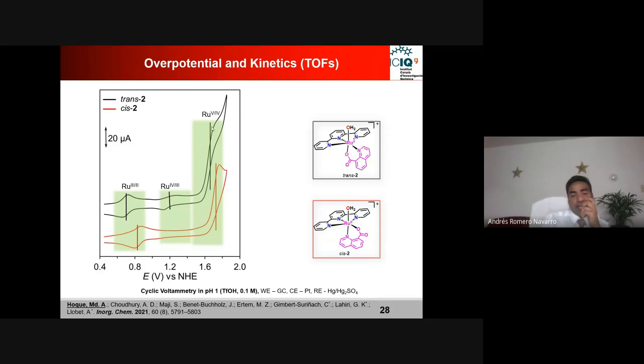And in the case of water oxidation, as I mentioned, we need the high valent metal oxide species in order to do the nucleophilic attack of the water molecule. And this high valent species is the ruthenium-4,5 oxo complex. So here you see that the black line is the trans isomer, and the red is the cis isomer. So the structural environment is exactly the same, but the relative disposition of this carboxylate group is changing the overpotential.